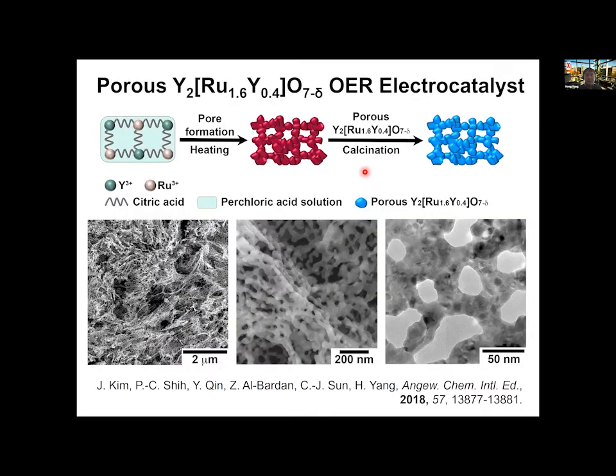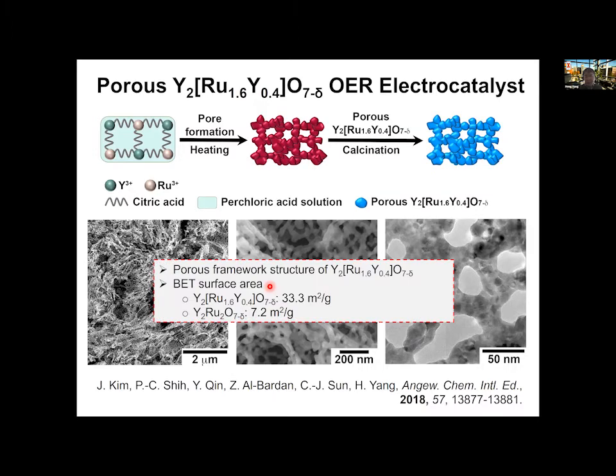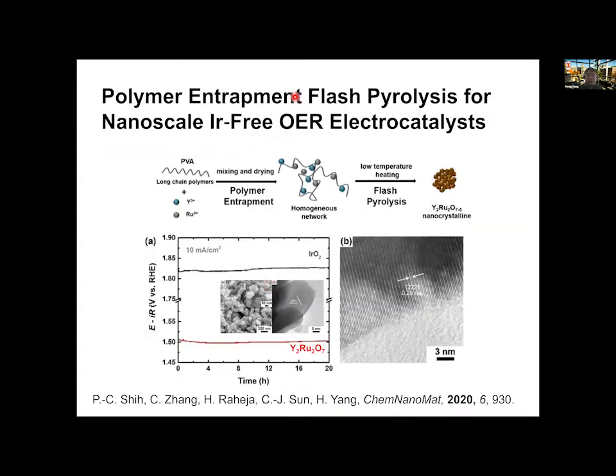And beyond the system itself, we also try to increase the surface area by creating porosity. One approach is the so-called porogen approach, to create the pores while it's calcinated or pyrolyzed during the conversion step. This work was published a few years ago, 2 years ago, in Angewandte Chemie. Another approach is to use an entrapment method to make nanosized ceramic, quote unquote, because this is an oxide after all, and try to make that into a nanoparticle size and increase the surface area. So those are some of the efforts that go into the oxygen evolution catalyst development.